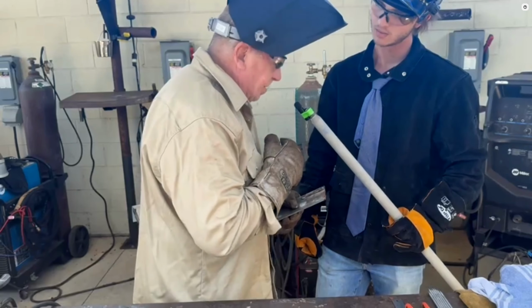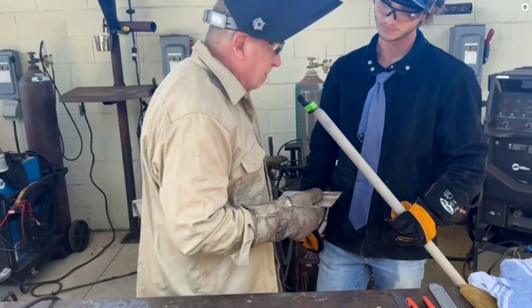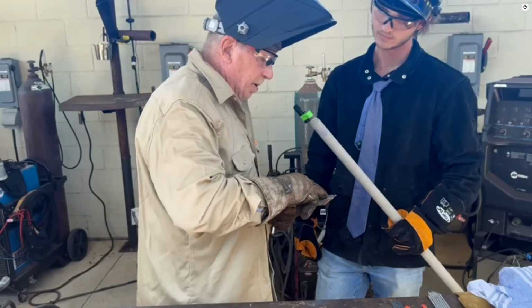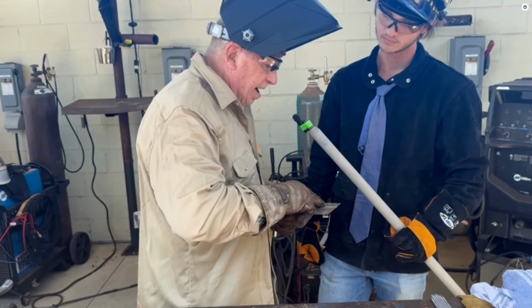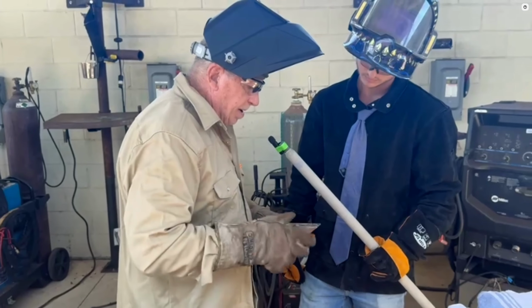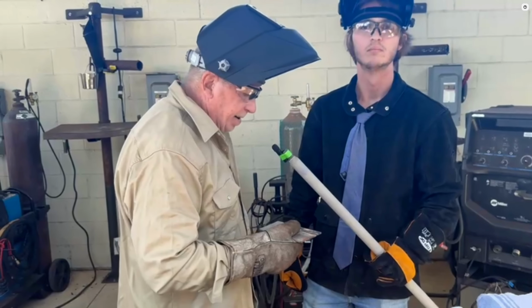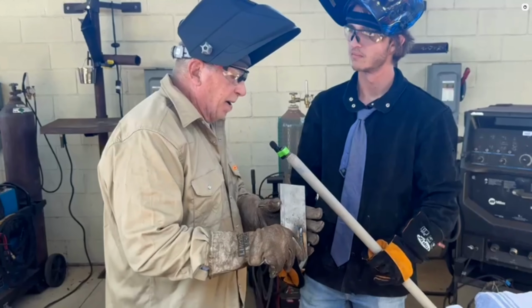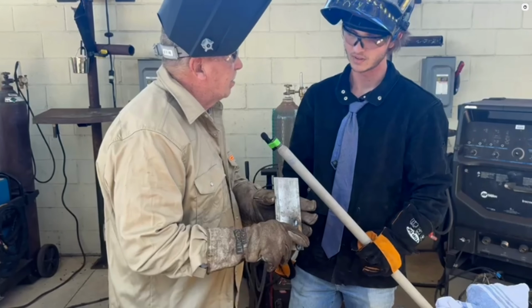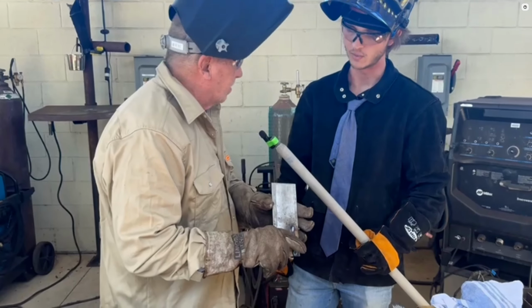So we need to check your amps. Check your amps on your machine. And then I see where you sped up, which flattened out your weld. So what we're going to have to do is check the amperage on the machine, and then we want to measure our plate because we're running too thin a plate for that amperage.